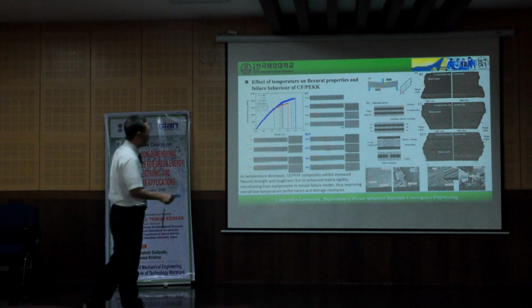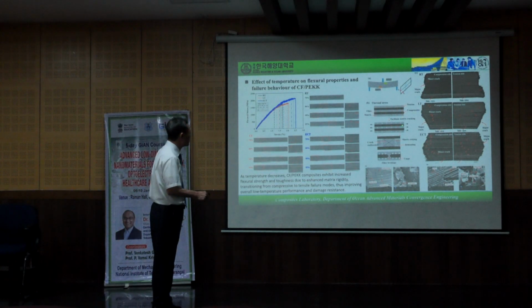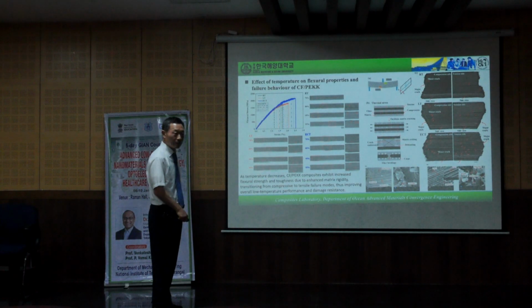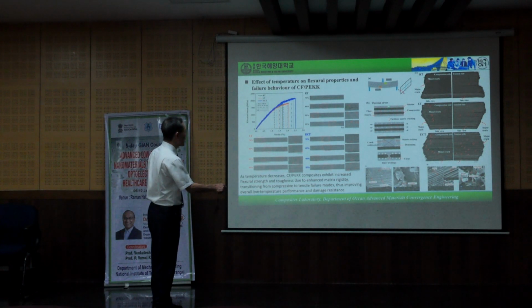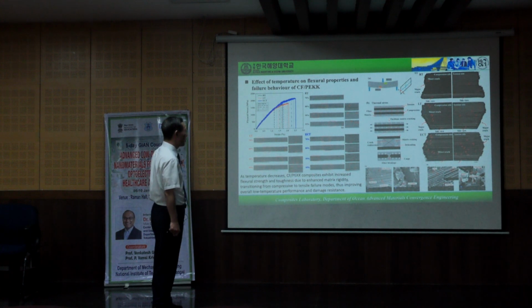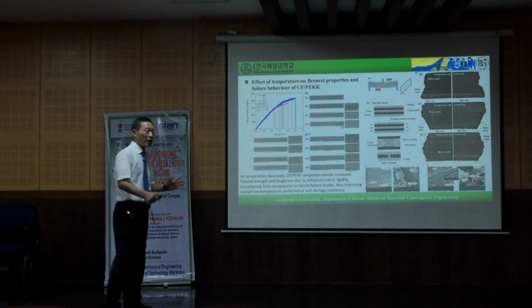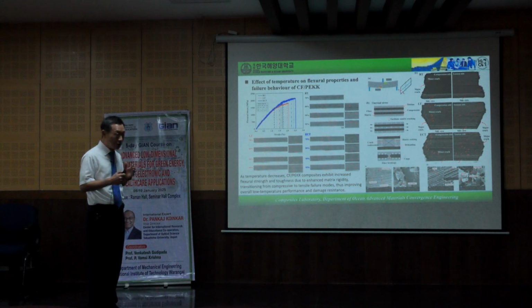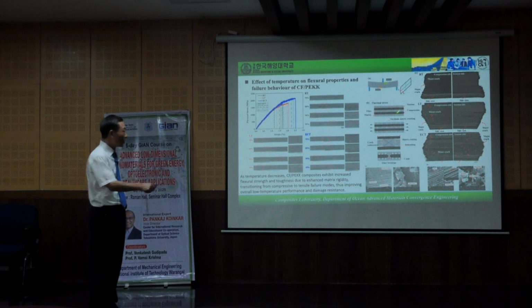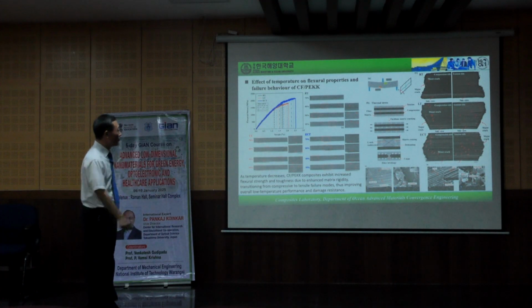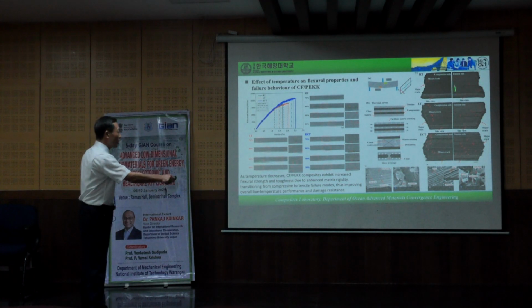Just look at this mechanism. Thermal stress will be occurred like this. In case of fiber, under compression, and matrix under tension. This kind of residual stress will be occurred here. The fracture mode will be changed.